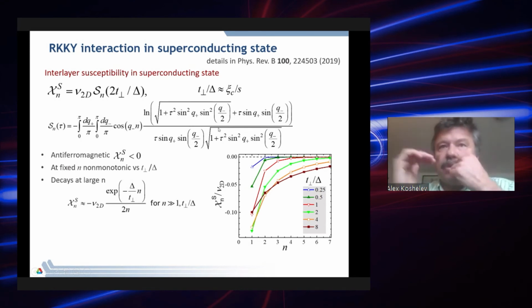I would summarize several important things of this contribution. First of all, it's antiferromagnetic. It's always smaller than zero. If we fix the layer index, it non-monotonically depends on the ratio. Actually, the next neighbor reaches maximum when this ratio is about 2.4. And of course, at large distances, it decays exponentially, as you would expect in the superconducting state. Nevertheless, if this ratio is large, superconductivity makes RKKY interaction long range. It's kind of counterintuitive that superconductivity actually enhances interaction between layers rather than decreases it, as one may expect.